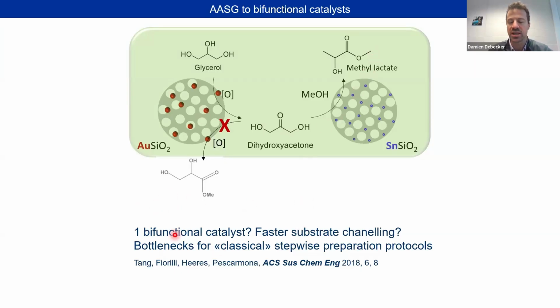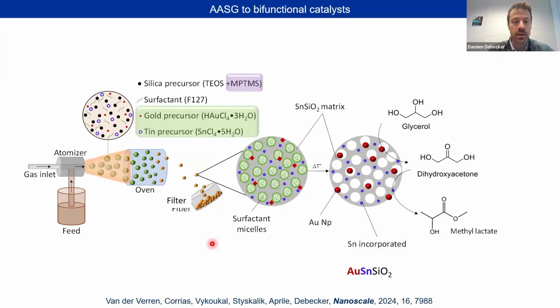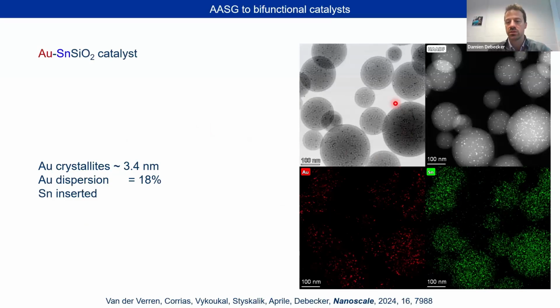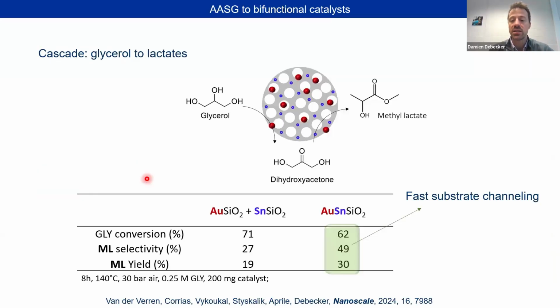So for this, we will need the bifunctional catalysts, and we were not the first to try. Some other people tried with classical stepwise impregnation methods, and it was not really successful. So we thought, why not trying it with our technique by putting, of course, our magic trick here, MPTMS, the gold and the tin precursor. So same concept, and indeed we characterize again, we keep a very good dispersion of the gold, we keep a good insertion of the tin, we indeed check that we have a good dispersion by the titration technique, and indeed